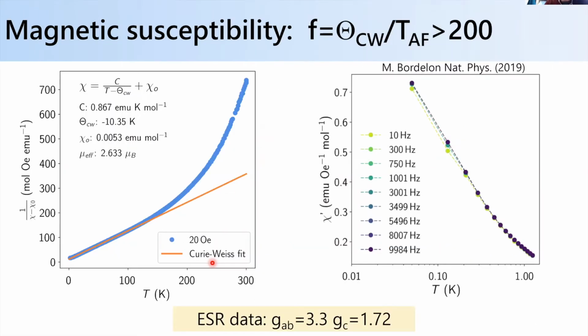Okay, good. So now if we look at the magnetic susceptibility of this material, we can plot the inverse magnetic susceptibility as a function of temperature. And we can do a Curie-Weiss analysis, which looks a little weird. You see a deviation up here at high temperatures, because as you heat up above 100 Kelvin, you start to populate this excited state doublet around 30 milli-electron volts or so, and that obviously changes your magnetic susceptibility. But if you measure below 100 Kelvin, where you've frozen out all of those excited state doublets, then you can get a reasonably good Curie-Weiss analysis. And we can get an exchange field, which is pretty high for a ytterbium system. It's about 10 Kelvin, okay? And it's antiferromagnetic in sign.